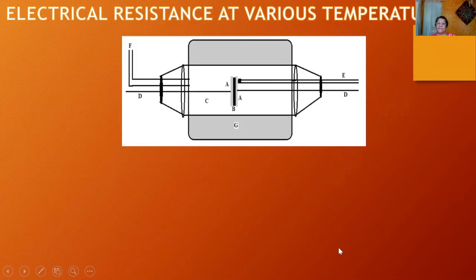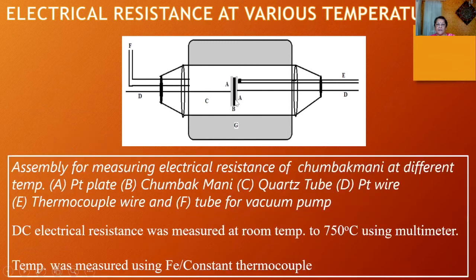Then this is electrical resistance, how we measured. So this was our setup. You can see this is our platinum plate, and the central black one is our Chumbak Mani, and then it is attached. It is kept in a quartz tube. This is a quartz tube, and platinum wire here and here, they are there. And the thermocouple wire is this, but as I told you, it was difficult for the thermocouple to perform, and it was done under vacuum.